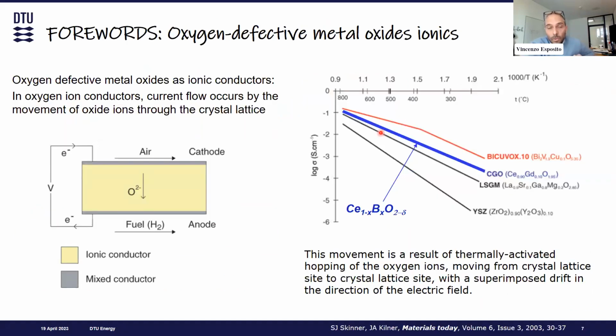Again, we knew these materials as oxygen ion conductors, and this is where they have been applied, for sensors and fuel cells and electrolysis at high temperature. This is because those defects at high temperature are actually mobile, and we can transport oxygen vacancies through the structure just by applying an electric field. What you see on the right is a typical Arrhenius plot at high temperature. We are talking about 500, 600 degrees C for these materials. They lack an oxygen, and the oxygen is basically the charge carrier.